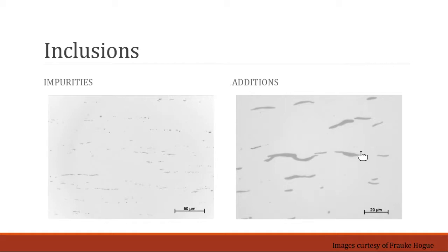Those are in the form of manganese sulfide. In the pipeline industry, any of the high strength, low alloy steels, it's unwanted. All it really does is reduce the fracture toughness of the material. But why would you then add sulfur into steel? Sulfur is typically added, as in the image here on the right, for better machinability. You're able to cut the samples better and machine whatever parts you need to, but those would not be something that you would want to depend a lot on for structural